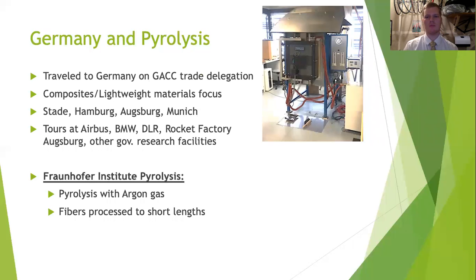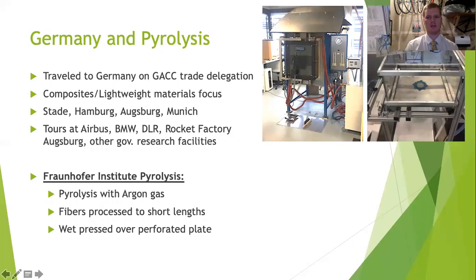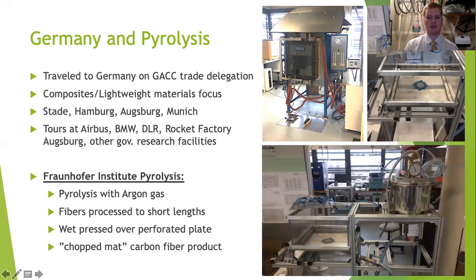Where they had to set up a machine for that exact process that I wanted to study. In fact, this is where they invented composites pyrolysis. So in this process, the noble gas argon is used to help stabilize the burning process. The fibers are cut into short lengths, and then they are wet pressed over this plate that has a bunch of indentations in it. And then the result of this is a nice chopped mat carbon fiber product, which is sometimes used for insulation under hoods in cars and things like that.